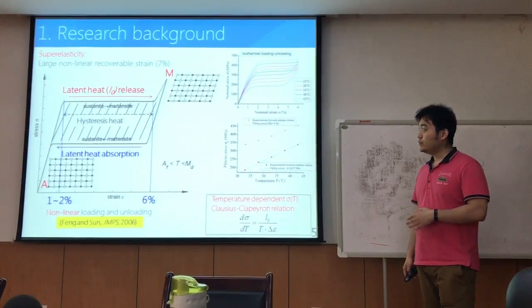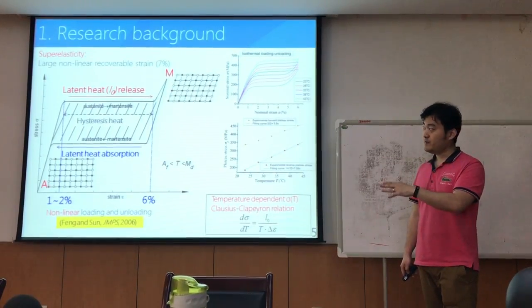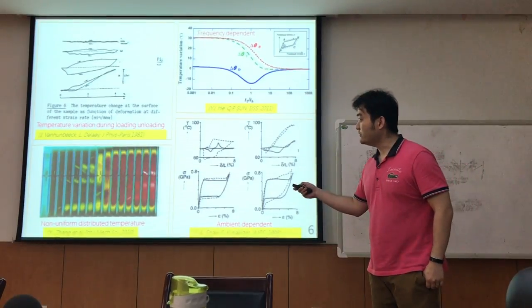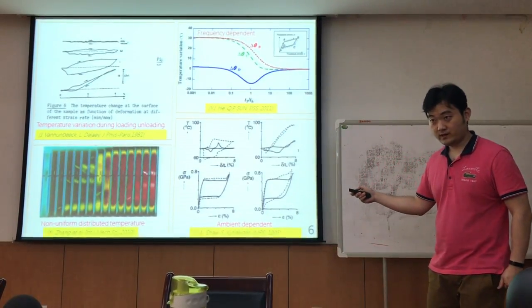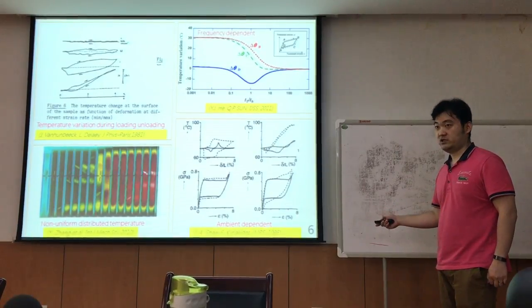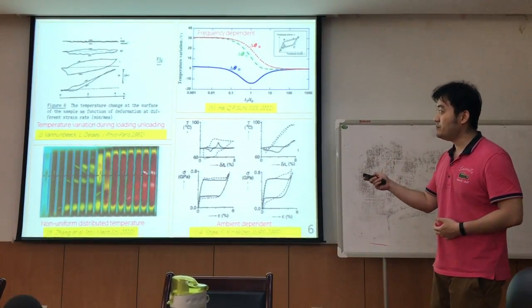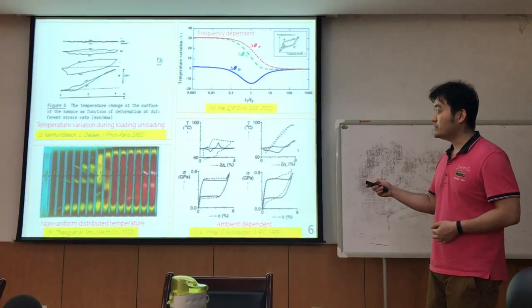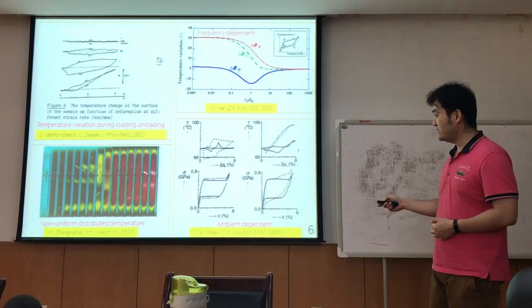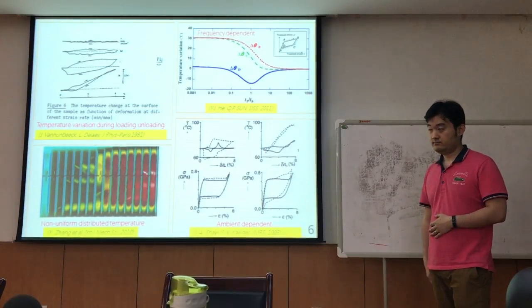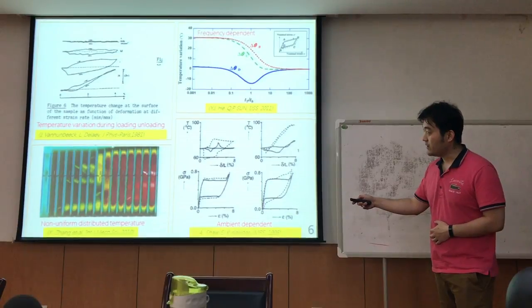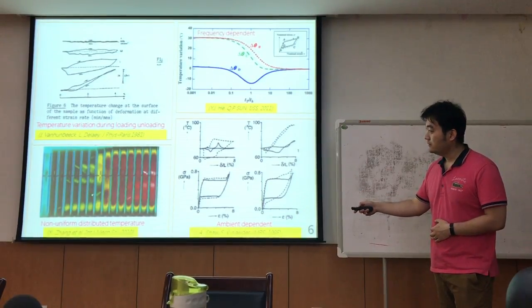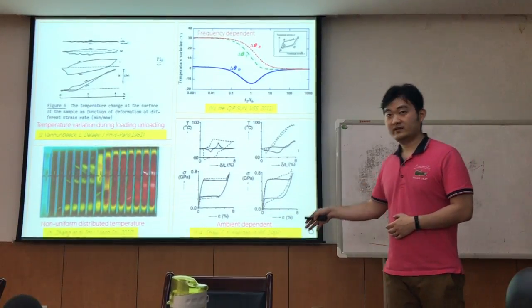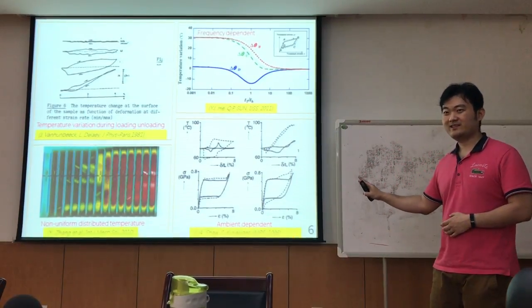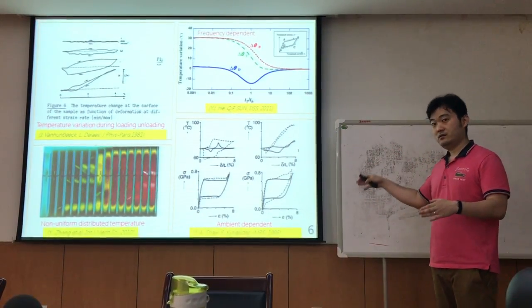Okay, so with these properties, people find out that with different strain rate, or in different ambient conditions, the temperature history and the stress strain curves vary a lot. Okay, this is because with different strain rate, the specimen's temperature under this loading-unloading cycle is different. Since the stress is temperature dependent, the stress will be affected.